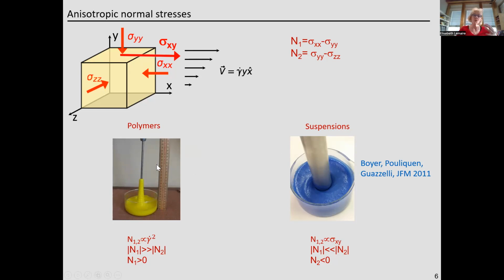And for instance, if you make the very simple rotating rod experiment, so it just consists in rotating a rod in the material. If you do that with a polymer, you are going to observe that the polymer climbs along the rod. But for non-Brownian suspensions, you observe that the suspension dips near the rod. Okay.